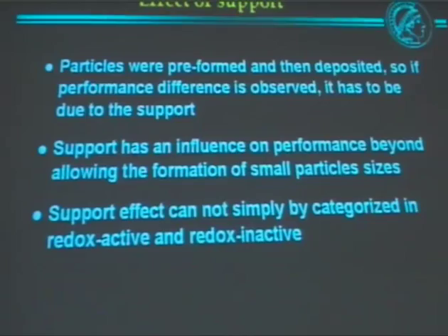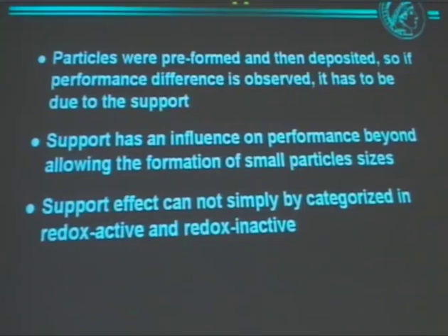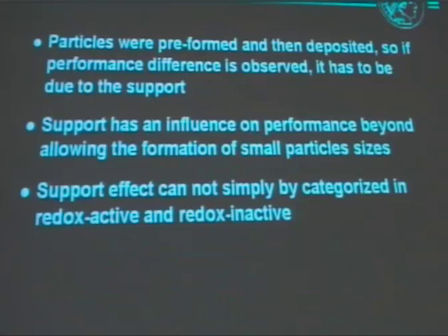So this summarizes this part. The support has an influence on the performance beyond allowing the formation of small particle size, because with the same particle size, with the same synthesis route for the colloids, four different supports have four different, widely different activities, from minus 10 to plus 100. This is orders of magnitude in reaction rate. And it's certainly not that the support effect can be categorized in redox active and redox inactive supports. There must be something else.